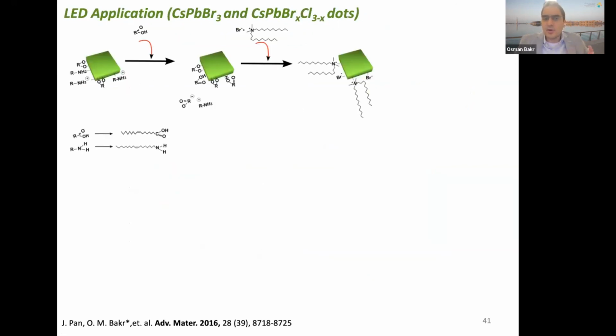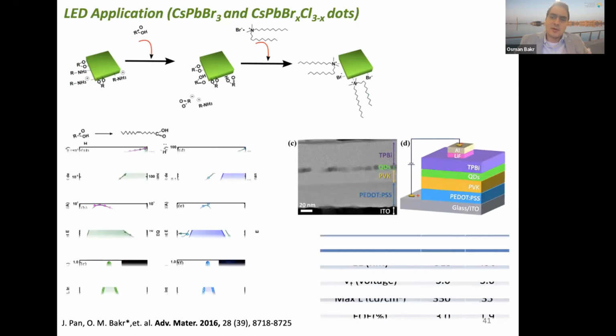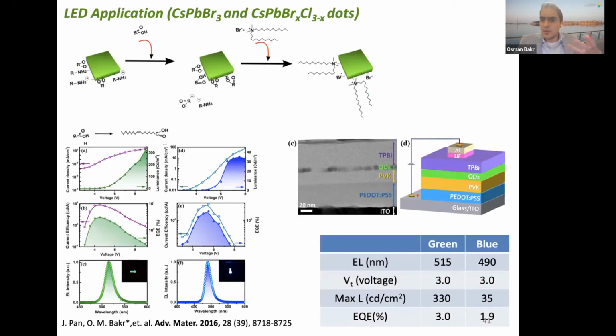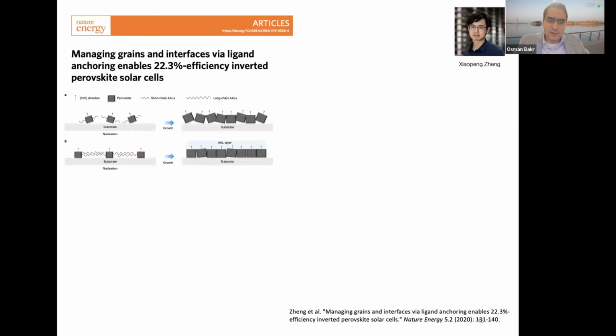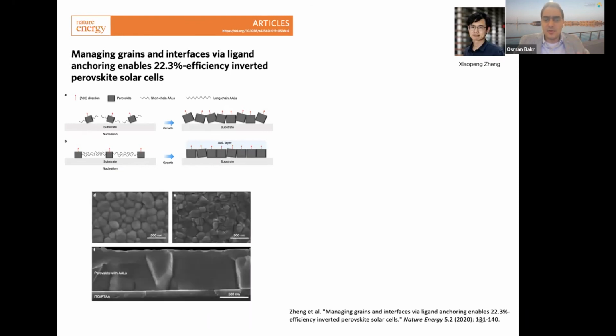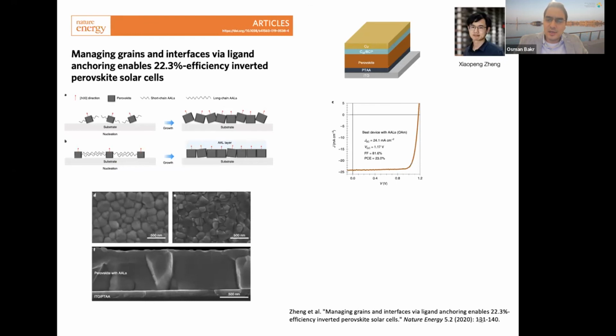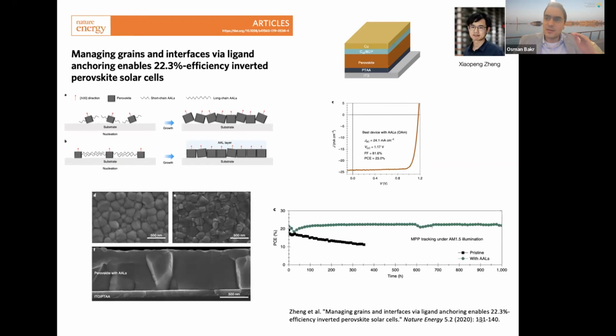And we were able to show at the time a record blue LED. Now blue and green LEDs are much more advanced in perovskites. The efficiencies are very high, and they're very exciting at the moment. But at the time, these numbers were quite high, and they were a record. We were also able to show that some of these ligand exchange concepts that we developed for nanocrystals, we could apply to passivate solar cells, and we were able to obtain record efficiency solar cells for PIN devices. At the time, they were record efficiencies, and they were able to show that these devices can be stabilized.